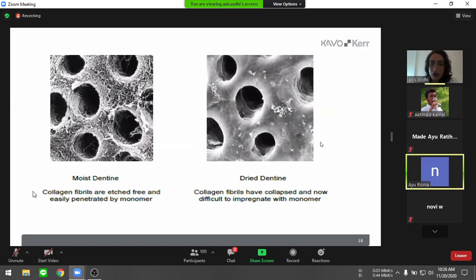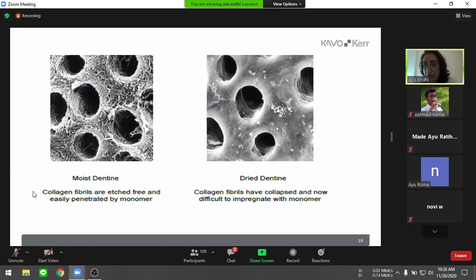So that was a pictorial representation. Now let's look at an SEM image here. This is a moist dentine and this is a dry dentine. A dry dentine is going to look like this in an SEM image. Now, as you're practicing and you're looking into the patient's mouth, how can you tell? What is the clinical indicator? So, dry dentine is going to look very dull, right? A moist dentine should be glossy. So that means that in this dentine, the collagen fibers are not very dry. In the moist dentine, the collagen fibers have not dried out. They have not collapsed. They're still pretty available and standing, right? So when we apply the bonding agent on top of it, it is going to percolate into the microscopic spaces and seal those open gaps.